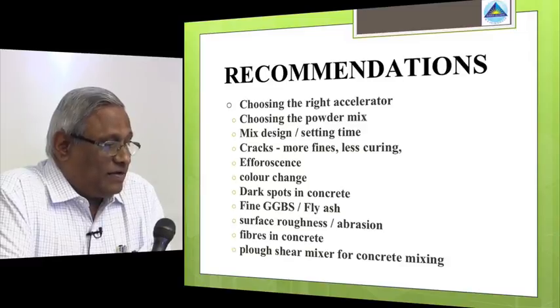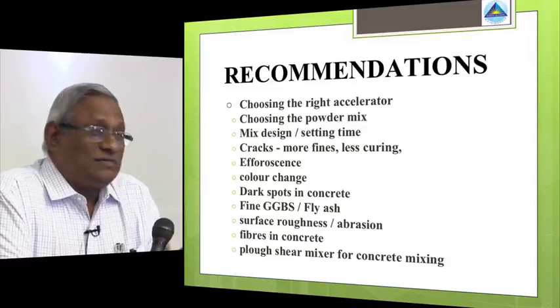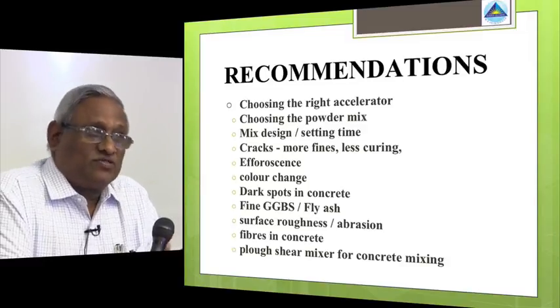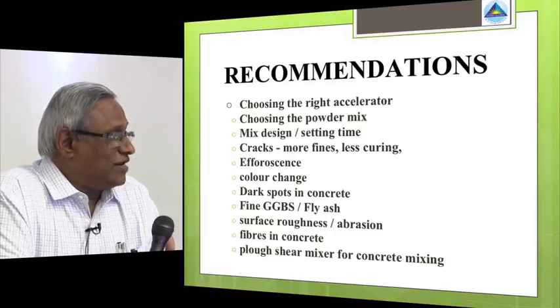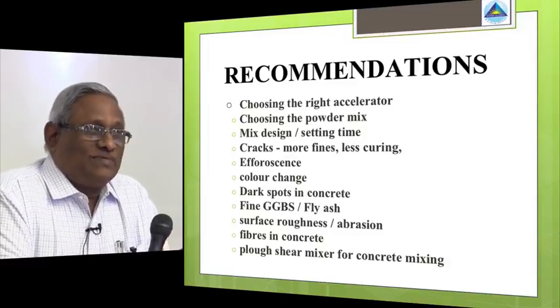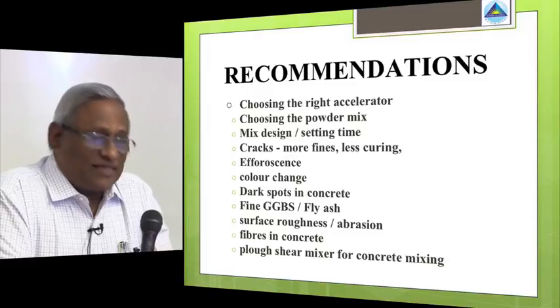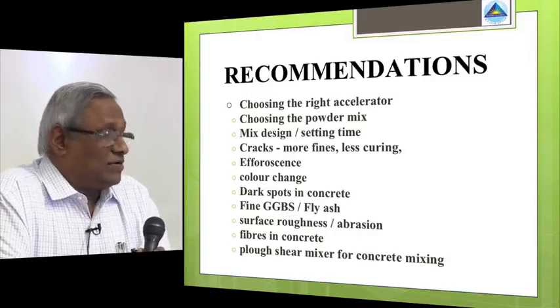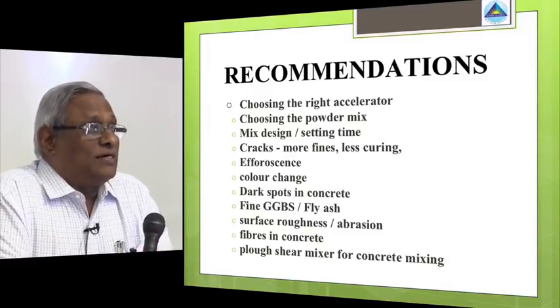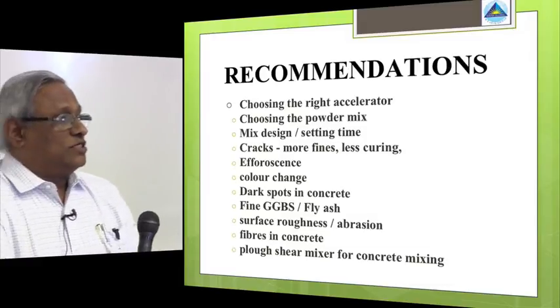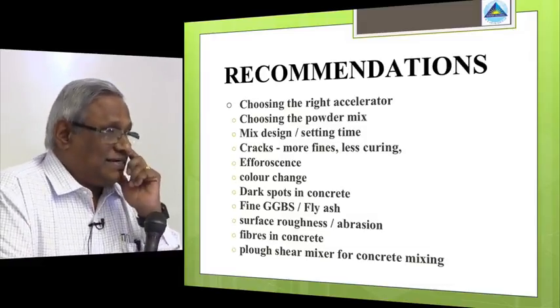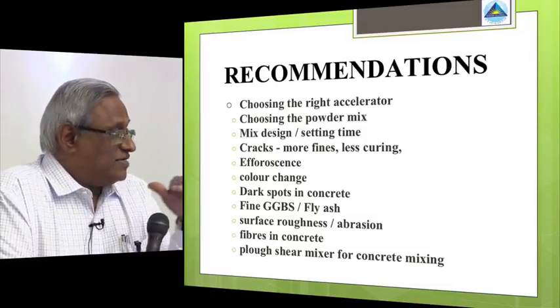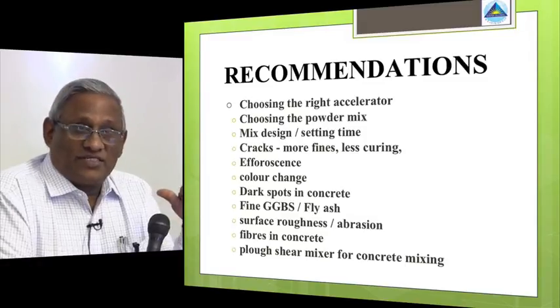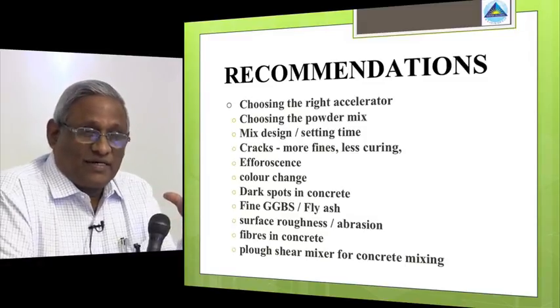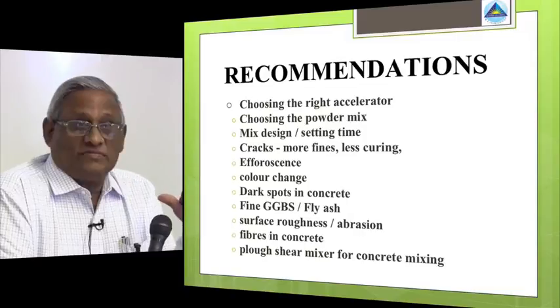And the more fine of GGBS and fly ash is also not good. You have a lot of fines, you have a lot of problems. So you have to work on a proper particle size to have the right concrete. Another important issue that normally comes to all geopolymer precast products is the surface roughness or abrasion. It tends to be soft in most of the cases, but it could be made hard, very hard.